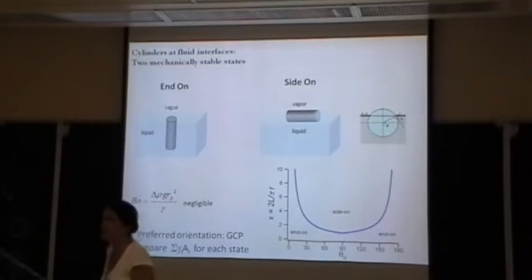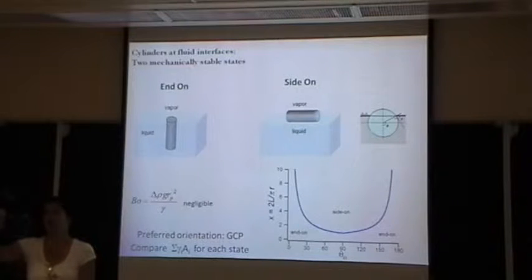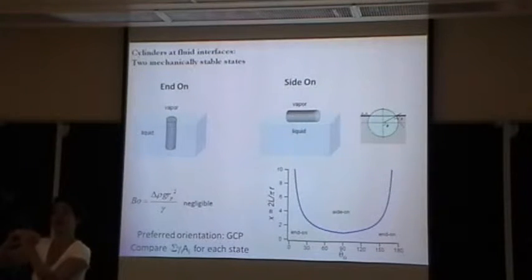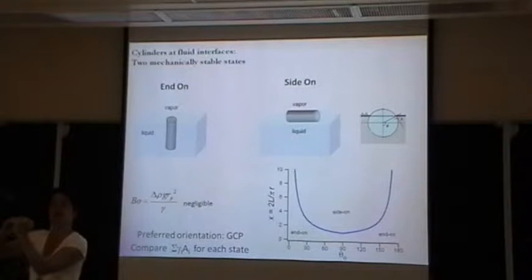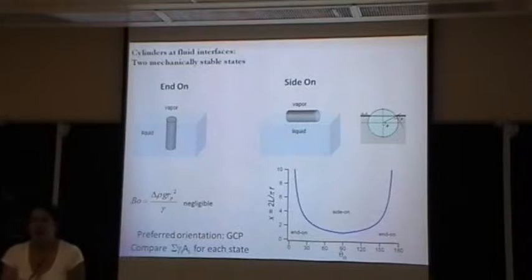And so there are funny things that cylinders have to make you think about right away. A cylinder can satisfy its force balance at the interface by lying on its side. And we already know something about the distortion that's going to happen. If it's partially wet, we'll have some rise at the end, which pulls down. And there has to be some upward pulling along the sides that pulls up. And you can see already that makes it be a quadrupole, right? Up and down.